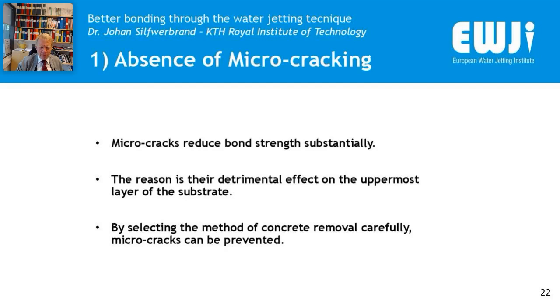So I will speak some words about the five main factors first. So we have this absence of microcracking, and microcracks reduce bond strength substantially. That has been shown in several research projects. And the reason is their detrimental effect on the uppermost layer of the substrate. The microcracks are rather superficial, but still they are producing a top layer of the original concrete that is weaker than the base. And by selecting the method of concrete removal carefully, microcracks can be prevented.